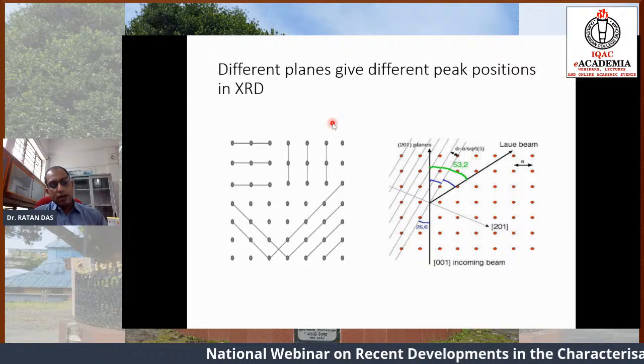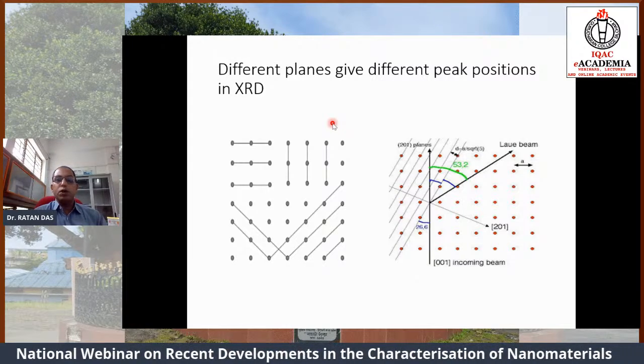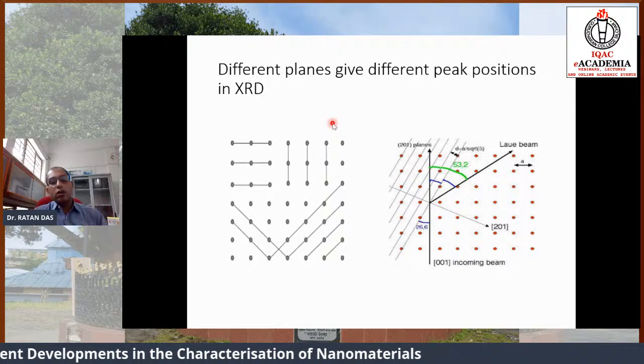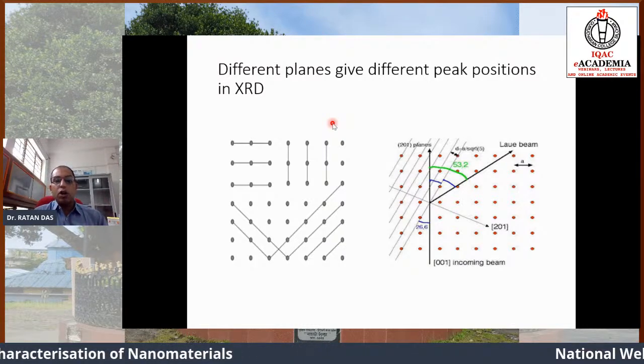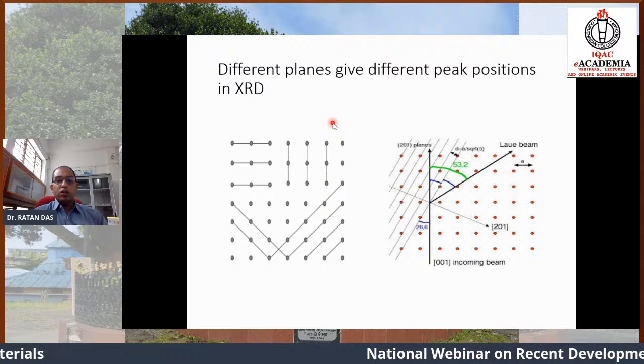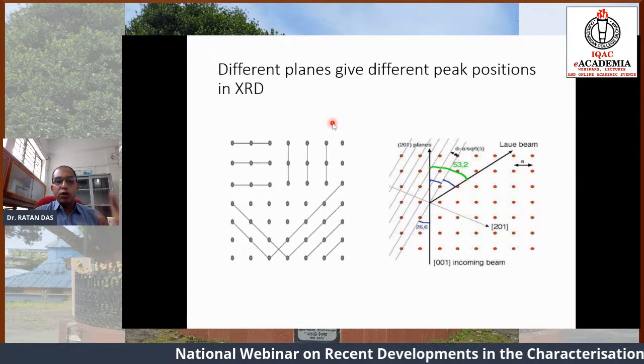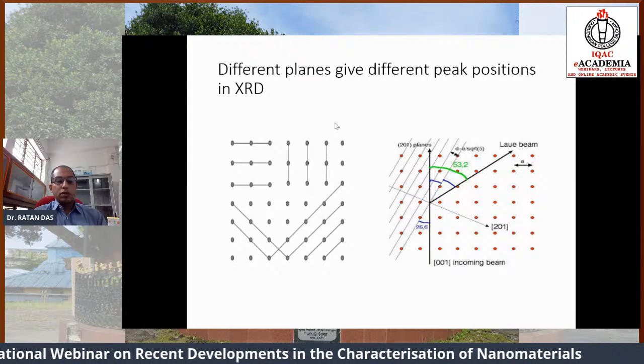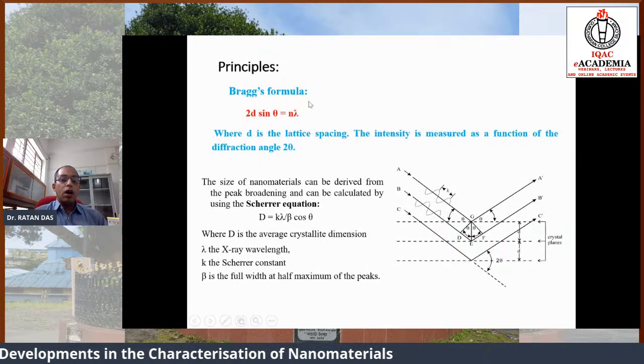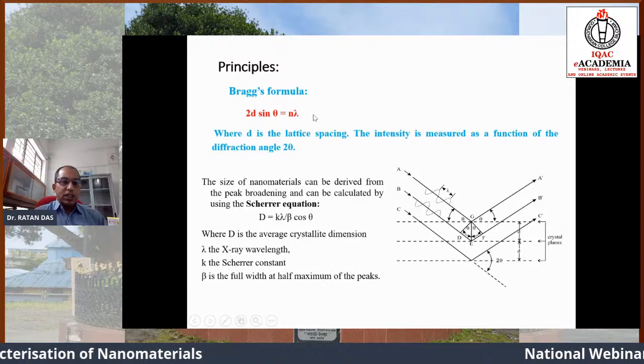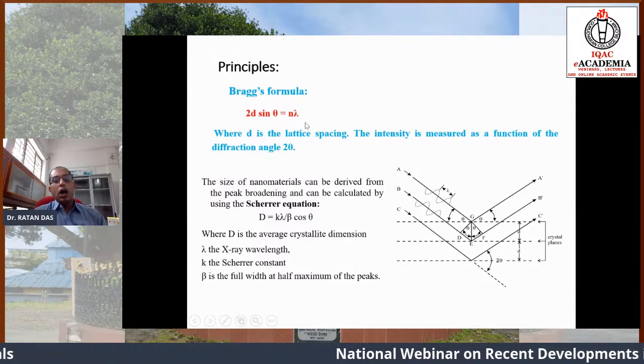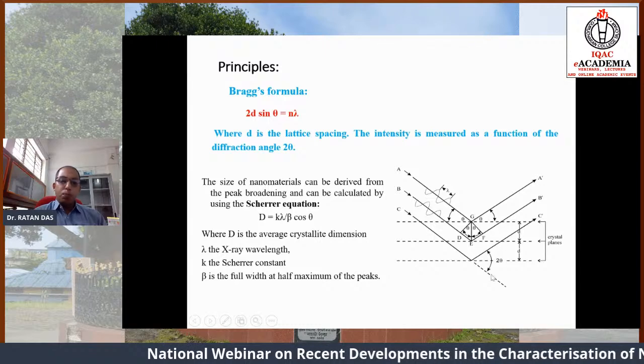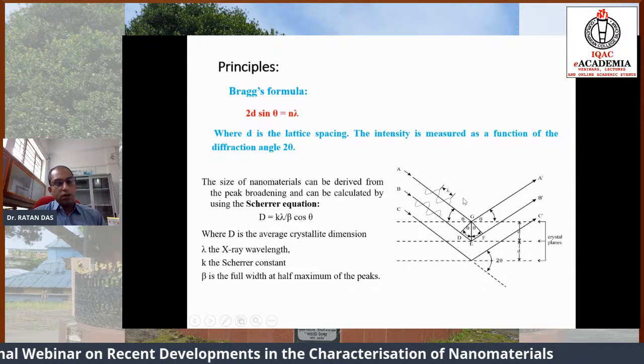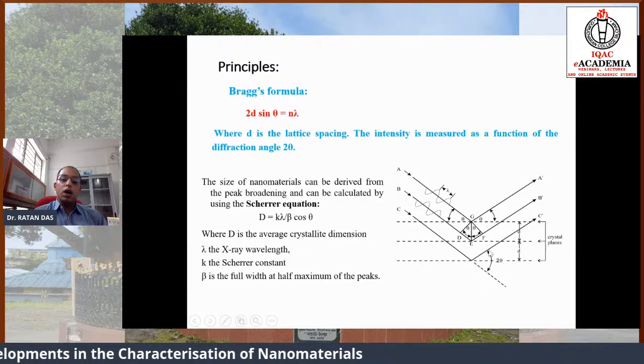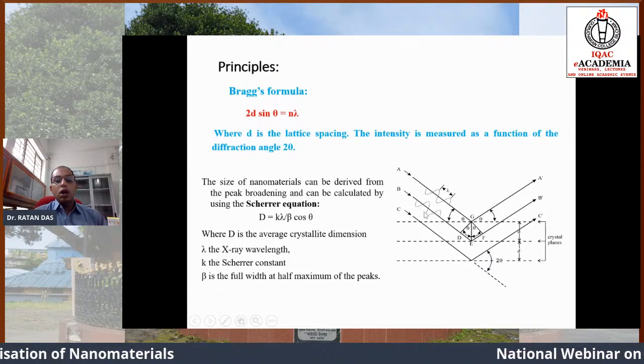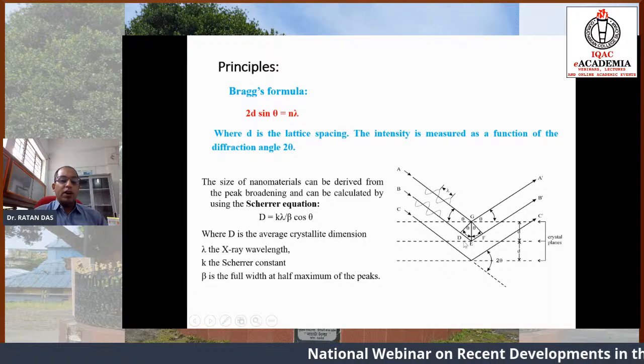Suppose at a 30-degree angle we get a particular peak position or higher intensity. Then at another angle, suppose at 40 degrees, due to another particular plane, we may obtain another diffraction peak or higher intensity because of the satisfaction of Bragg's formula 2d sin theta = n lambda. So what I want to say is that different planes give us different diffraction patterns because different planes make different angles with the detector.